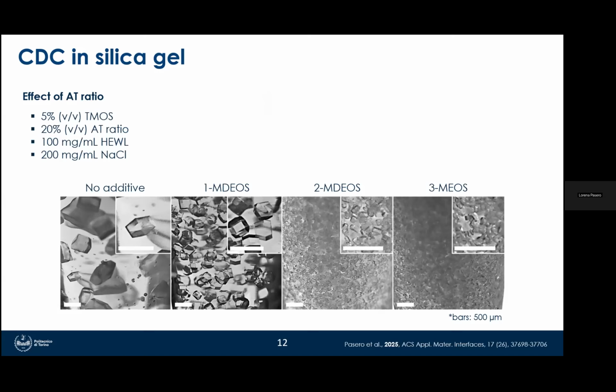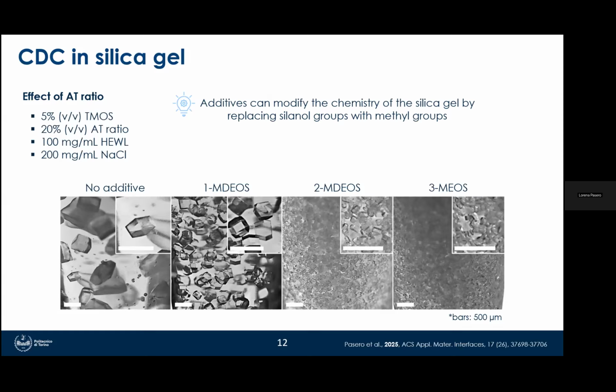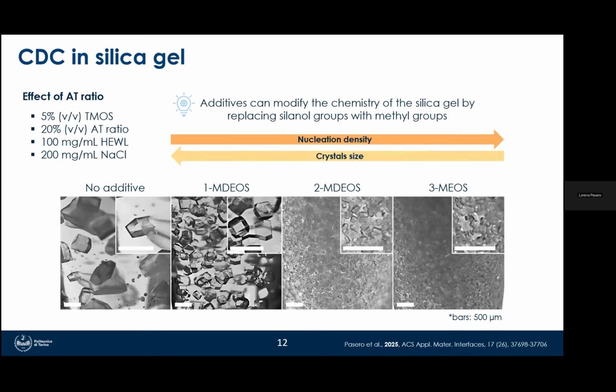We could see that in this condition where 5% TMOS was employed, the additives could effectively modify the chemistry of these silica gels by replacing the silanol groups with methyl groups. And this resulted in an increased nucleation density as the number of methyl groups employed increased. And this also led to progressively smaller crystals, since we had a higher supersaturation and higher formation of nuclei, and so nucleation prevailing on crystal growth.